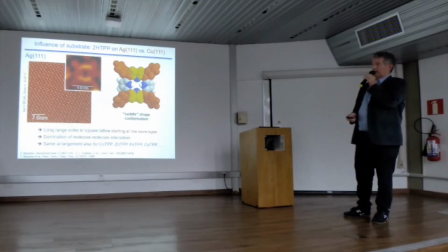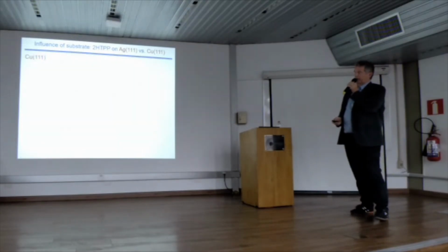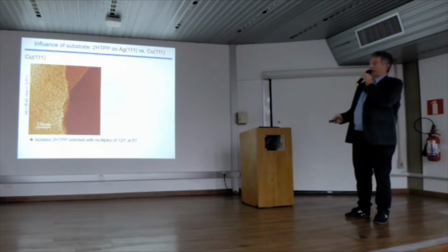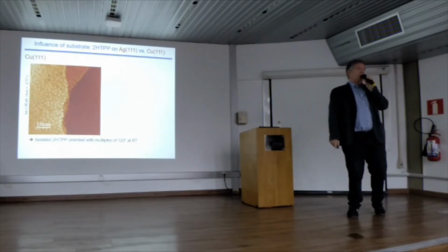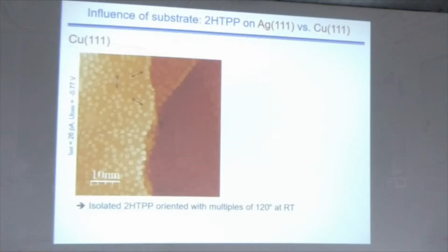And with copper, the story is completely different. If we go to the copper surface, we don't have ordered layers. We have disordered adsorption, seemingly disordered adsorption, because we see individual molecules, they look a little like butterflies. There are 2 bright longish protrusions and a dark line in between. And if you look in a little more detail, they are not really randomly oriented. There are only 3 types of orientation.